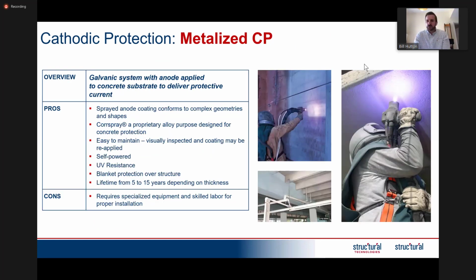Another system, which is also galvanic, so there's no power supply, typically life up to around about 15 years. So this is called metallizing. So metallizing is where molten zinc is actually sprayed by using compressed air onto the surface of the wall. So we'd start the installation by installing a metal plate onto the wall, which is connected to the steel. So that becomes your negative connection. You would then shot blast the wall, and then it's sprayed with probably up to about 200 microns of zinc, which can then be covered with an acrylic aesthetic paint if required. So this system is really nice because it provides a good length of protection, like I said, about 15 years, and very, very little operation and maintenance.